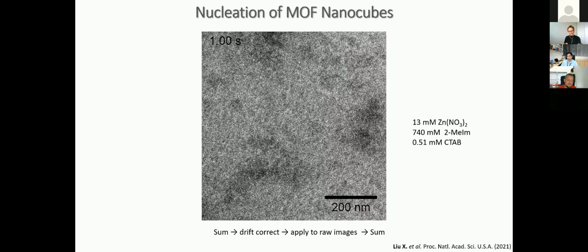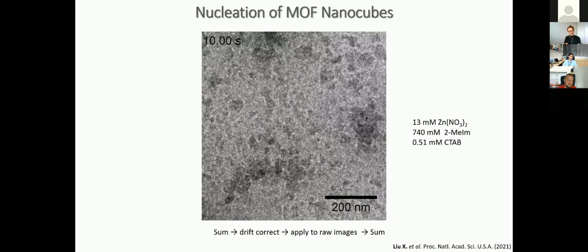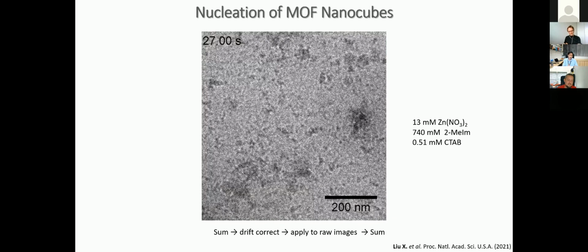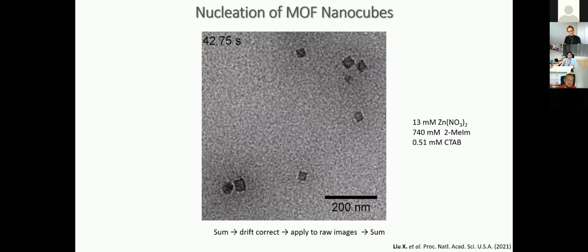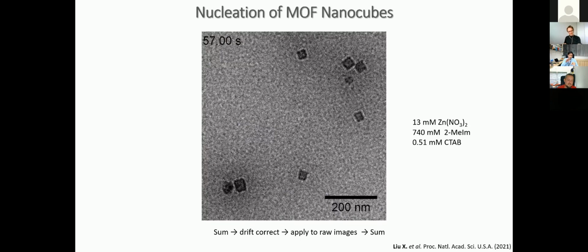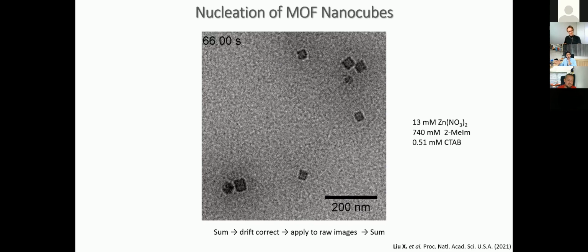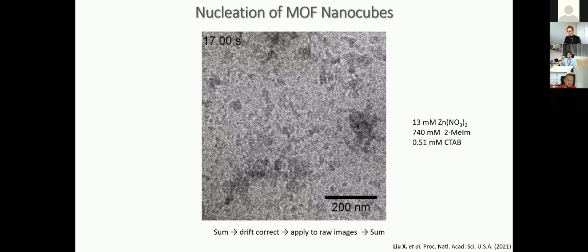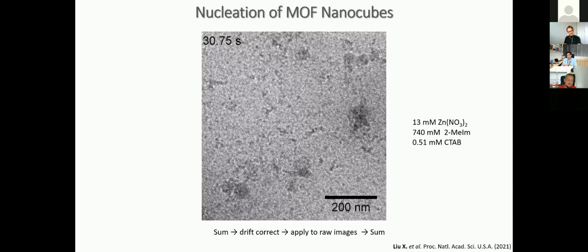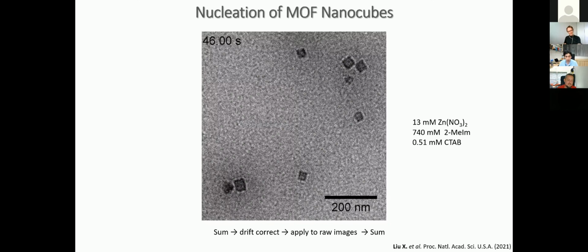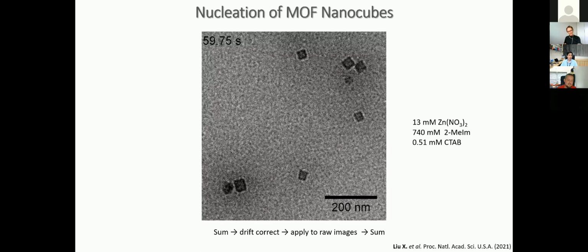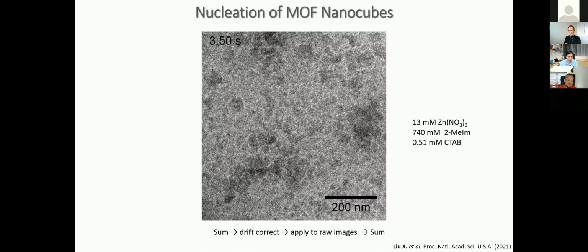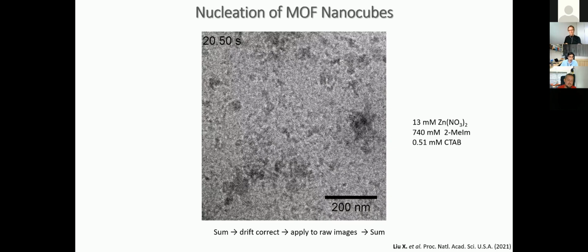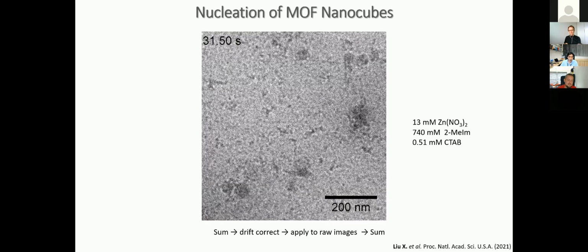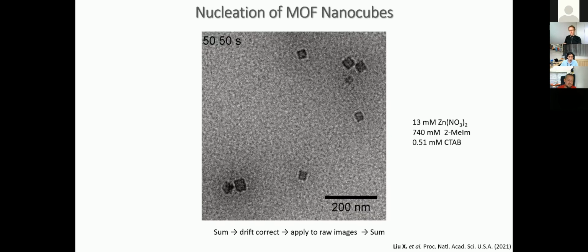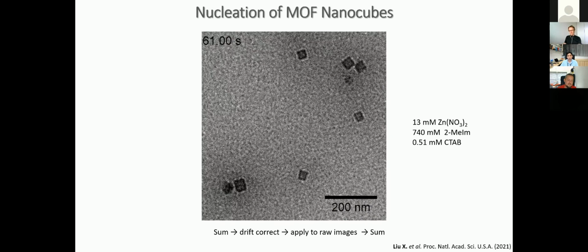This is like an average. So what you see in here is the image of the nucleation process. We average them, do the drift correction iteratively, and then we apply it on subframes. So we average 10 frames, and then we drift correct them. Then we apply this drift correction to individual frames within that average, and we keep doing it iteratively until we get this nice build-up image. And you see the formation of the nanocubes or MOF crystals. Again, what you see here, things phase separating, forming some amorphous-like aggregates, and then they're becoming kind of cubes, right?